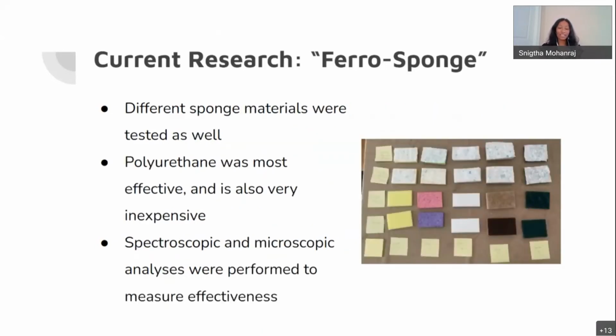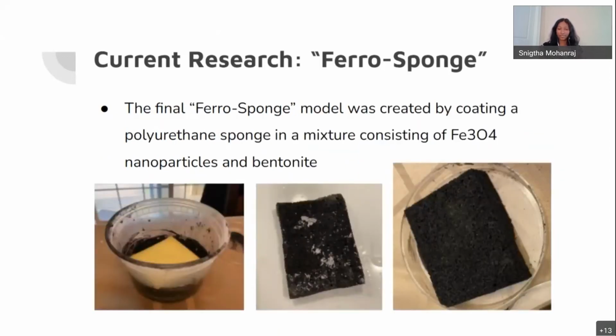In addition to the additives, I also wanted to test different sponge materials in order to see how the material would affect the efficiency of the sponge. Through these tests, it was shown that polyurethane was the most effective to be using, and polyurethane is also one of the most inexpensive materials, which is a huge benefit. Again, spectroscopic and microscopic analyses were performed to measure effectiveness across all of these different tests that I conducted.